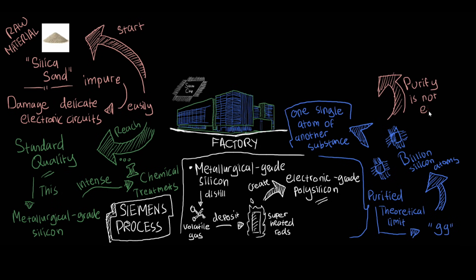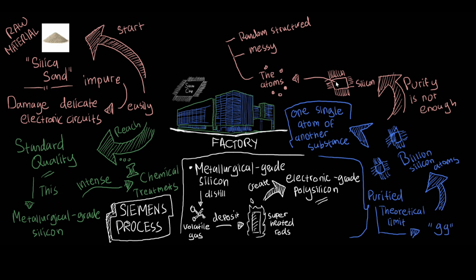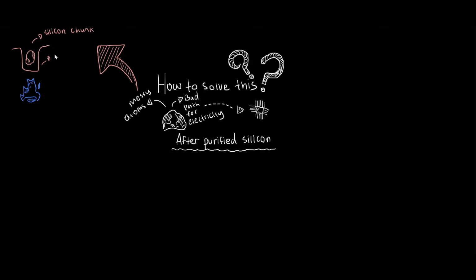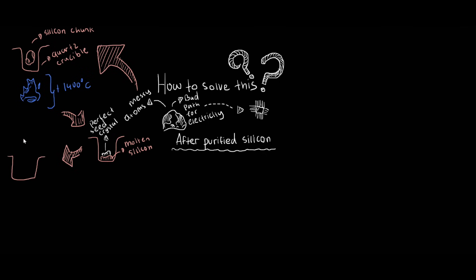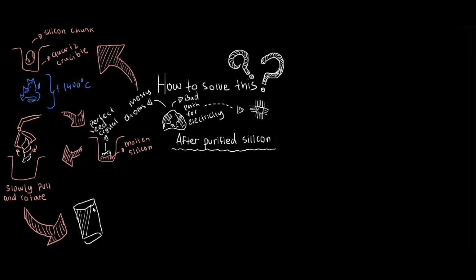However, purity alone is not enough because the atoms in the silicon are still arranged in a messy, random structure, and electricity requires a perfectly ordered path to flow efficiently. We solve this by melting the silicon chunks down in a quartz crucible at temperatures exceeding 1400 degrees Celsius, and then carefully dipping a perfect seed crystal into the molten liquid. By slowly pulling the seed upwards while rotating it, we encourage the molten silicon to solidify in perfect alignment with the seed, growing a massive cylindrical ingot that consists of one continuous crystal lattice.